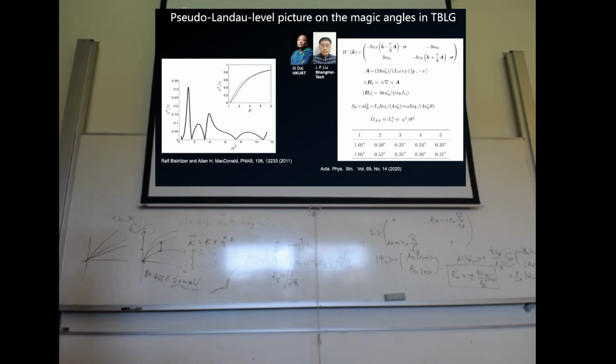And in graphene, the first row of data is taken from this paper from MacDonald, and the second row of numbers is very close to the first row, just by comparing these numbers when the two areas match each other. So apparently it's a very good, easy way to understand that this various curvature and effective magnetic field is playing a role in the flat band in the system.